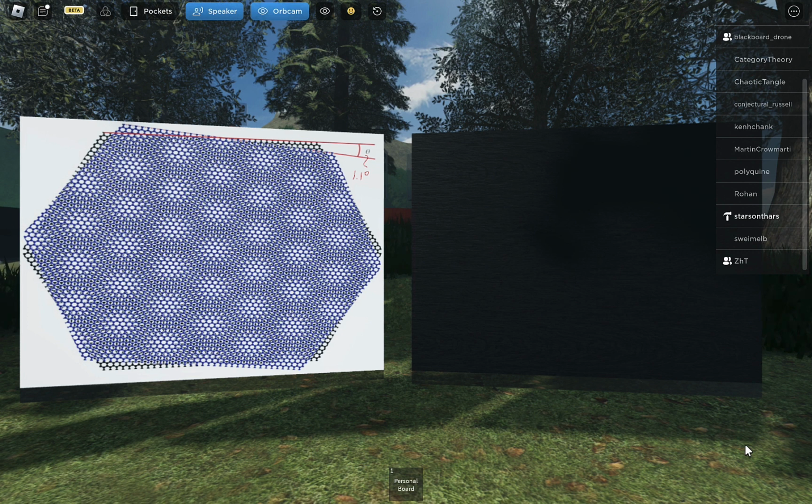So in 2018, well, it's been predicted for a long time that graphene has special electrical properties, and there was even some theoretical reason to think that superconductivity might arise in bilayer graphene. But in 2018, it was an experimentalist group, if I get this correct, that discovered that if you layer graphene at exactly this angle, you get a superconductor, this two-layer material, at about 1.7 Kelvin.